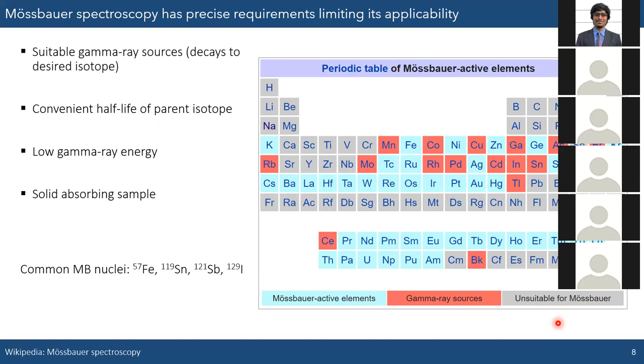You also need to have a pretty low gamma ray energy, which is what prevents some elements from being used for Mössbauer spectroscopy. Because if very, very high gamma ray energies are required, you're going to have issues with the recoilless emission, because you're putting in very high energy gamma rays and you're going to get a lot more lattice vibrations present.